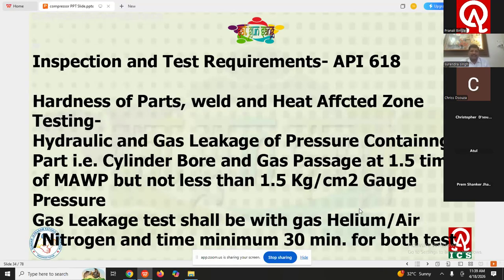Okay, now after the visual inspection, we have to check the hardness of the part, maybe on the parent metal part, then the welding. If welding is there, then we have to check the hardness on the weld area, then on the heat affected zone. Any other testing which is required in the QP, you have to also witness. Now coming to the testing part, the hydraulic and the gas leakage test of the pressure containing part as per API 618 to be carried out, that is cylinder bore and gas passage at 1.5 times of maximum allowable working pressure.